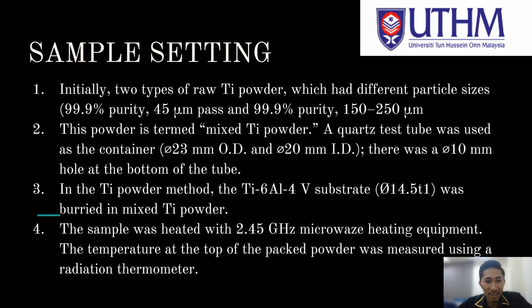Experimental method. Sample setting. Initially, two types of raw titanium powder with different particle sizes were used: 99.9% purity, 45 micron pass, and 99.9% purity, 150 to 250 micron. These two powders are termed mixed titanium powder. A quartz test tube was used as the container, with 23 mm outer diameter and 20 mm inner diameter. There was a 10 mm diameter hole at the bottom of the tube.